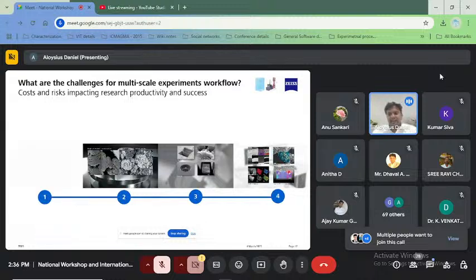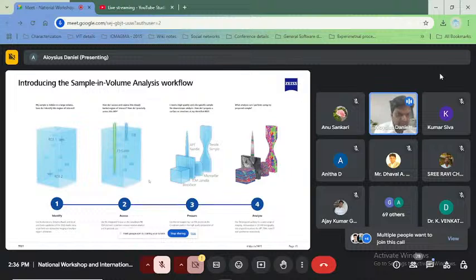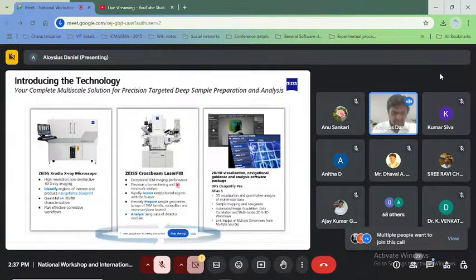So this is exactly how the workflow happens, with identifying using the X-ray microscope, accessing the area with a combination of both laser as well as ion beam. It's not only accessing, it is also used for preparing it. It could be for TEM lamella or atom probe tomography needle structures, or it could also be, as per the ASTM standards, you can prepare samples for mechanical characterization as well, which is then taken for the analytics like TEM analysis, crystallographic data collection, or mechanical characterization as well. So this is exactly what we do here. So this is the technology.